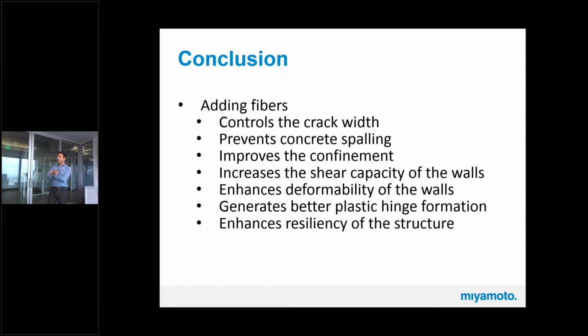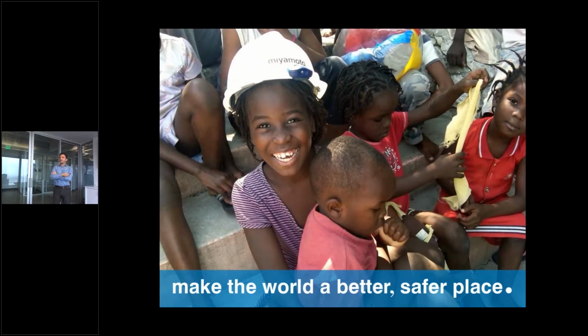Okay, so what we can conclude from this project is that in general, fibers control the crack widths, prevent concrete spalling, improve the confinement in the concrete and the structural elements, and more importantly, increase the shear capacity of the walls. And we can improve the deformability of the structural elements and their ductility by using fiber reinforced concrete. And also, we can have better plastic hinges with better performance and improve the seismic energy absorption capacity of the structure. And in general, improve the resiliency of the structure with lower investment. Okay, that was my presentation.